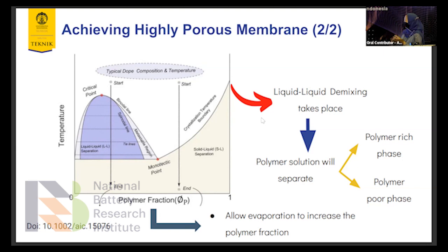The polymer solution will separate into two phases, polymer rich phase and polymer poor phase. But we need to remember that when we lower the polymer fraction, it has to be higher than the critical point, because if it's lower than the critical point, the membrane won't be formed. But if the polymer fraction is too high, it won't be separated into polymer rich and polymer poor phase, so there won't be any porous structure, and what will happen is solid-liquid separation. So we need to maintain the polymer fraction by maintaining the evaporation time.